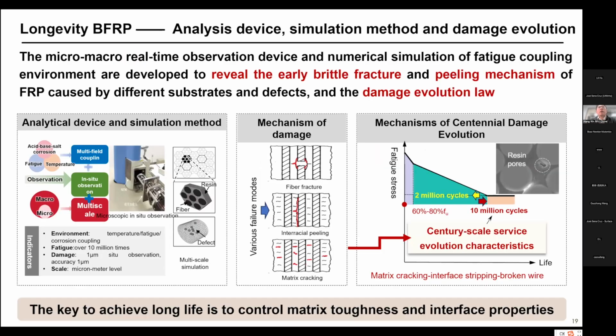So with this thinking, we developed a method that using a kind of in-situ observation tools. So by these devices, we can observe composite materials under fatigue loading with in-situ observation. So we can figure out its propagation of the damage under the fatigue, and finally we can understand the mechanism of the damage on a different level of fatigue, such as the fiber fracture or the interface debonding or some matrix cracking. So with this method, finally we understand composite materials under the long-term fatigue loading.